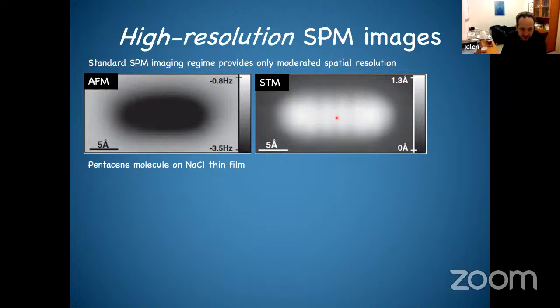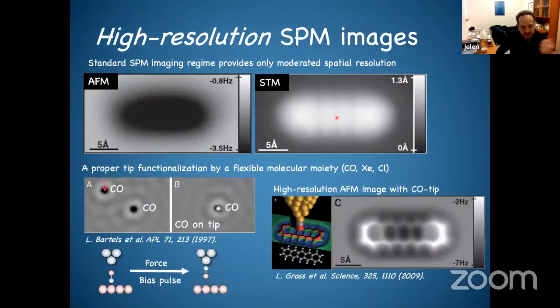But science is driven by accidents. What happened is that people had been working with CO molecules for a while. Then at IBM Zurich, one day, they just mixed two things together, these organic molecules and CO. And what happened is that CO came to the tip, so it was on the surface, and these guys picked it up. Normally when you have CO on metal, you see two dark spots, and then sometimes when you approach the metallic tip very close, you can pick up the CO. And how you know this is that the dark CO turns bright. So that's a signature that your CO is on the tip.